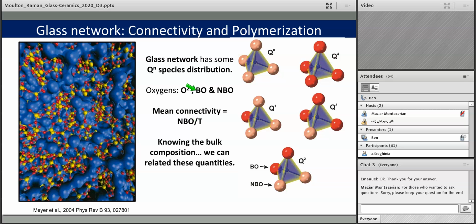If you have an independent probe of the bridging or non-bridging oxygen, you can calculate what the ideal connectivity would be versus what the mean connectivity is from the NBO over T, and these should add up. They should be related together. The total bridging oxygen and non-bridging oxygen should be related to how many bridging and non-bridging oxygen there are on the tetrahedra in your material. So we're going to take these ideas and play some games with them to try to test structural models that we can use for gaining insight for prediction of how the properties might change as the network changes.